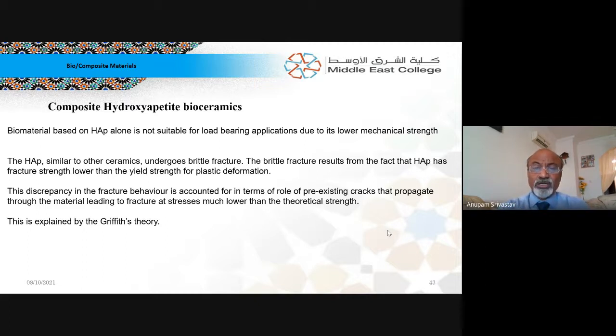If it is not a linear contraction or a controlled contraction, whatever you try, there will be pores and there will be cracks, and that makes these ceramics brittle, because with little tensile stresses given to the material, these pre-existing cracks join, propagate, and then ultimately result in failure, which is explained by the Griffith theory. So we have to avoid this in hydroxyapatite.